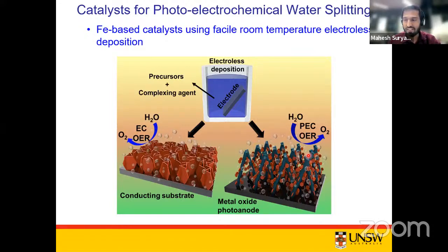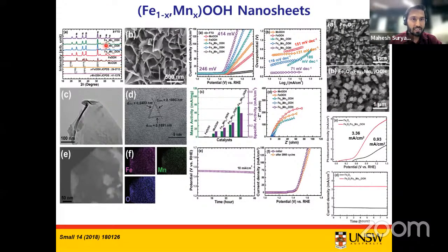I will quickly explain these results because I think I'm running out of time. We developed an electroless deposition approach to prepare this iron based catalyst, a first approach which avoids the use of excessive reaction temperature, as in the hydrothermal method, and does not require an external bias, as in electrodeposition methods, which are commonly used to prepare catalysts for water splitting reactions. We prepared an iron oxide catalyst and then incorporated Mn. After incorporating Mn into this catalyst, there is an improvement in the overpotential value to about 246 millivolt.